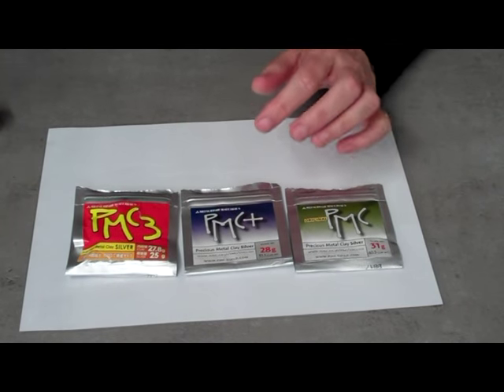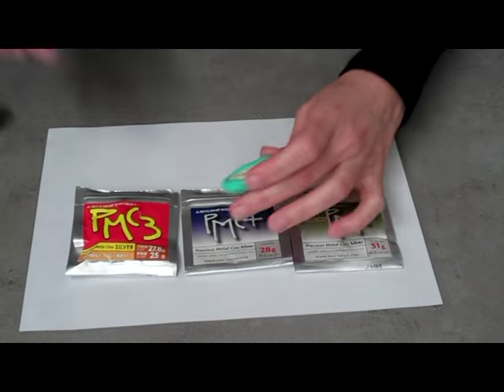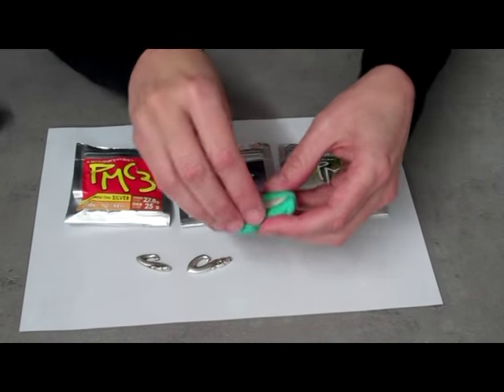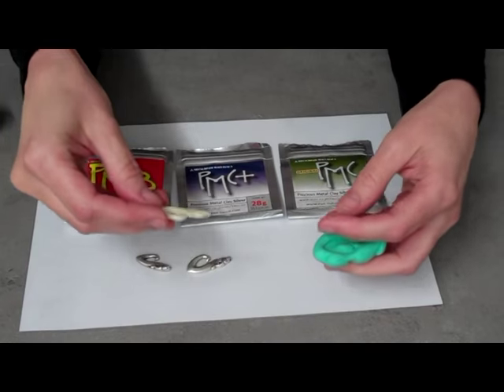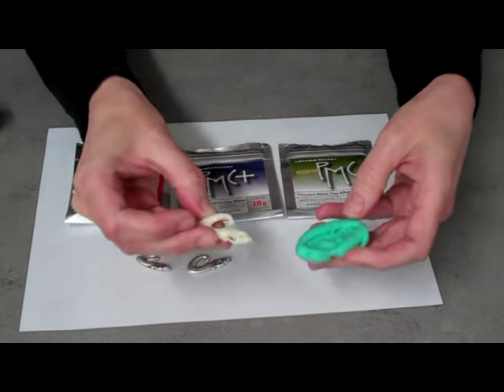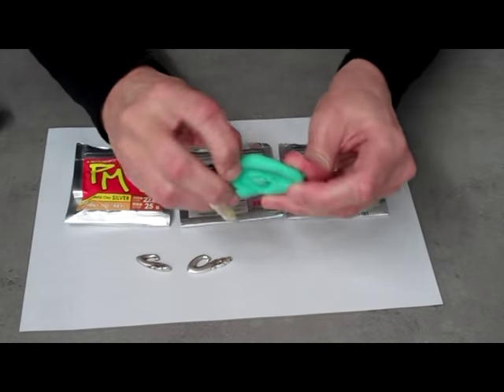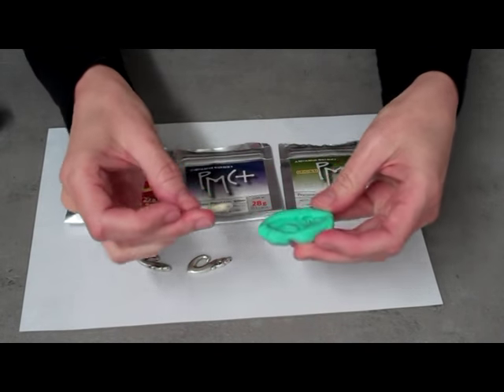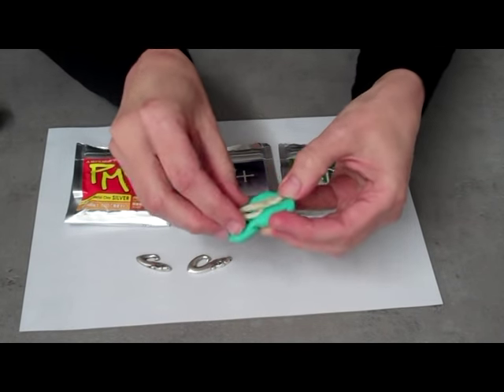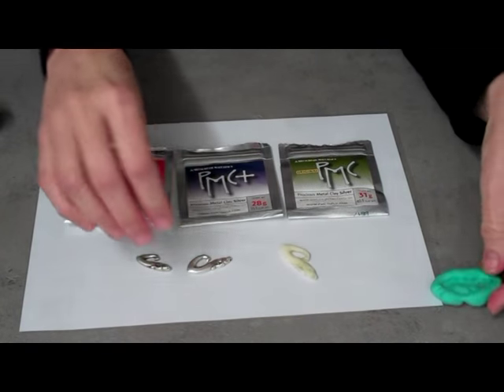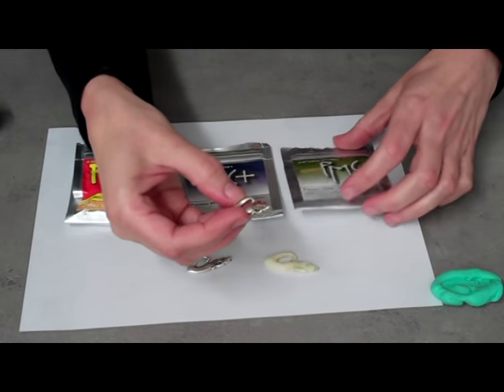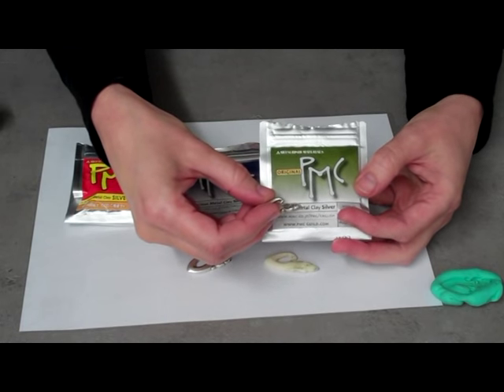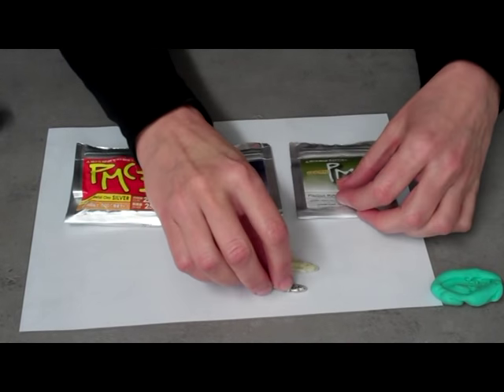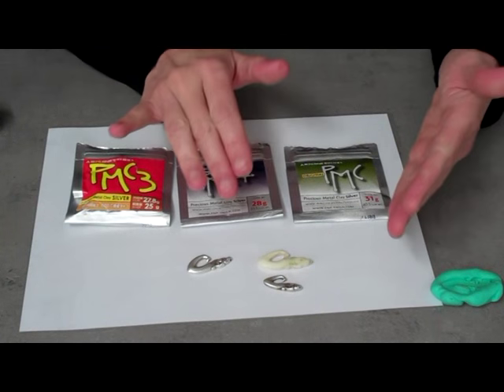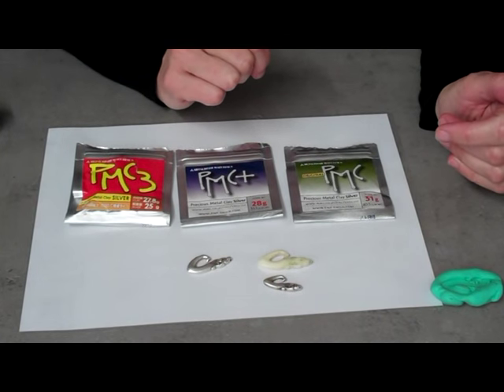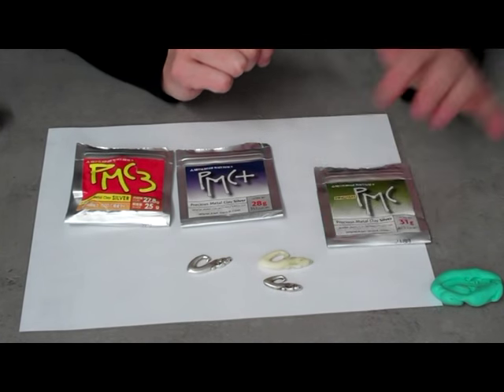So to show you what that actually looks like between the three different clays, because really percentages are kind of abstract to me, we've taken an original thing here that we've made a mould from, and you'll be doing some of this on the diploma class. We've made a mould from a one-sided thing here, and this first sample is from the PMC that shrinks by a lot. This is 28 to 30%, okay, so that's what that looks like. That's a visual representation of the 28 to 30% shrinkage in the kiln with the PMC original.